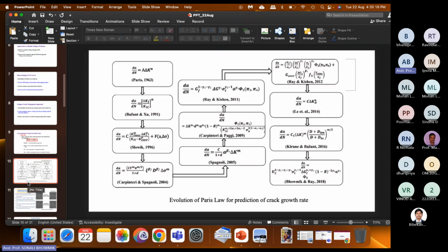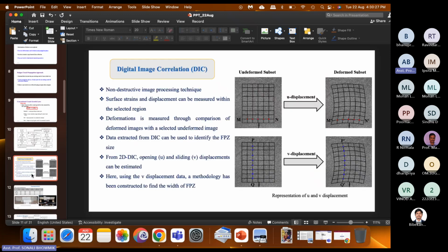But here, I'm working in the area of advanced crack detection techniques, which are non-contact techniques, DIC and acoustic emission. Here I'm explaining a few things of DIC, which is non-destructive. This is an image processing technique where we click images during the experimentation and compare both, the deformed image with the undeformed image. There are already software available, and also some open source algorithms available. One can refine, modify and improve those algorithms to find out the surface strain and surface displacement of materials.